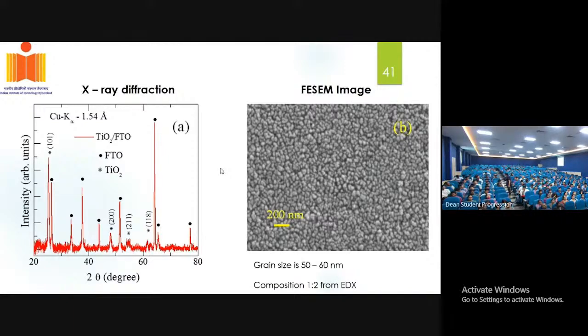Then we have to do the morphological study. If it is a thin film, what is the morphology? What is the roughness of your thin film? That is the most important thing. Then the phase of the material: in what phase has it been found? Using energy dispersive X-ray spectroscopy, EDX, you can know the composition of the material. Apart from that, you must also study the backscattered electron imaging, BSE, which gives you the different phases that exist in the material. Before you develop any device, these three are important characterizations that you must do: X-ray diffraction to determine the structure of the material, composition analysis using EDX, and backscattered electron imaging to know the different phases that exist in the material.